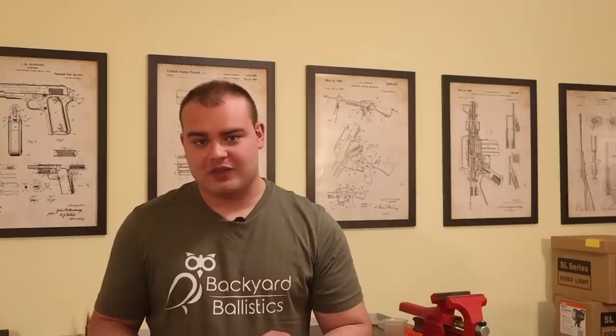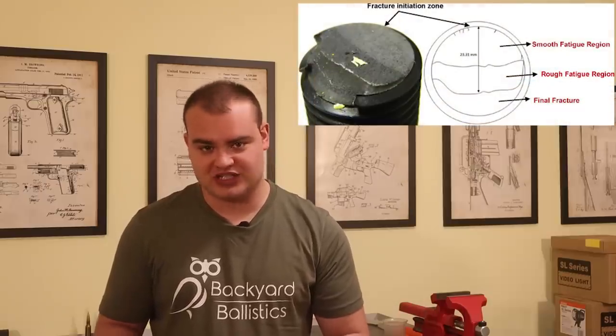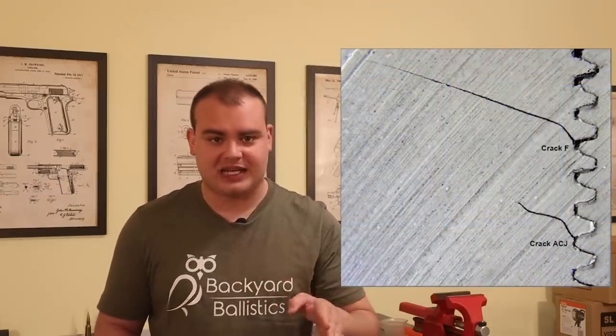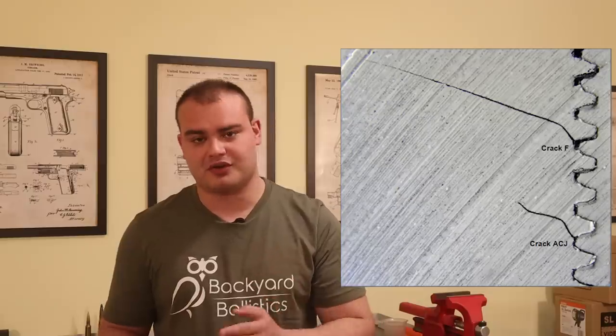But again, this implies that at each shot the threads should have deformed irreversibly. If that would have been the case, it would have soon become impossible to unscrew the cap by hand. Also, fractures due to fatigue have a very typical look, and tend to develop much more in tension rather than shear. They typically start from the root of the thread, because that's a stress riser, and then propagate into the material beneath, not along the thread.